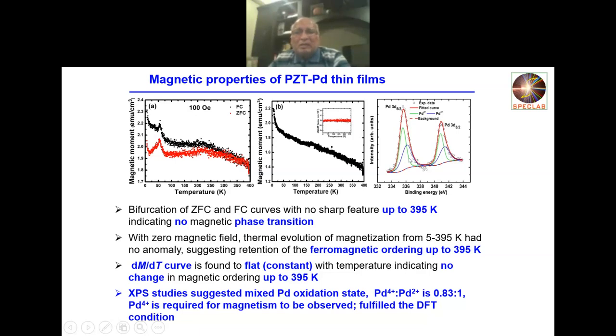XPS data, again, exactly the same kind of things. They tell the same story. That is, there is Pd4+ and Pd2+ occurring in this material. And the ratio was calculated to be 0.83 to 1. Pd4+ is something like 0.83 in this case.